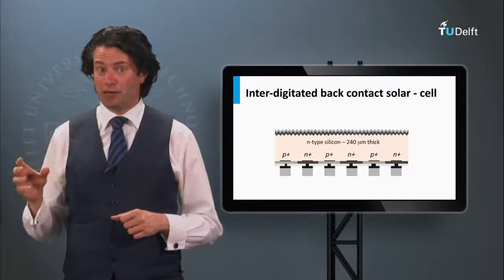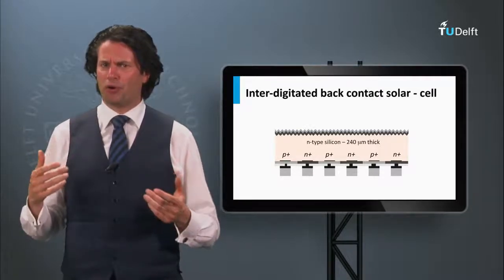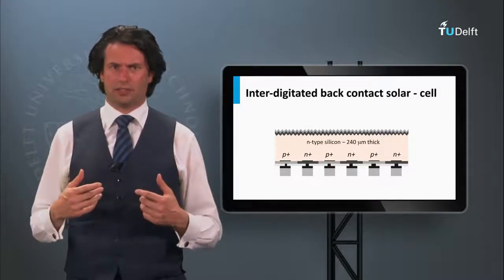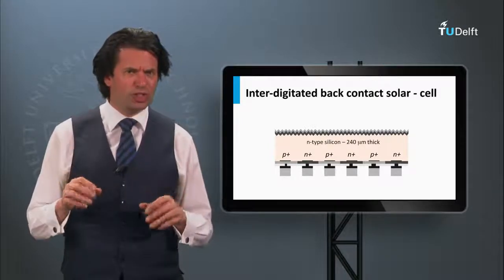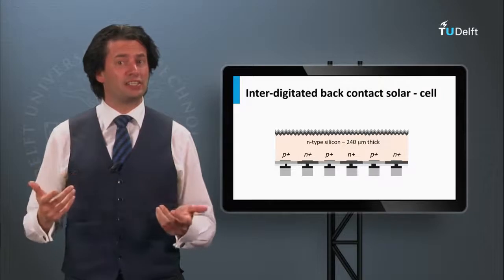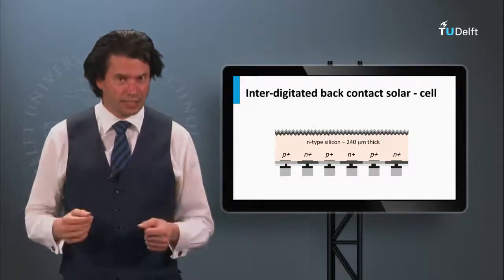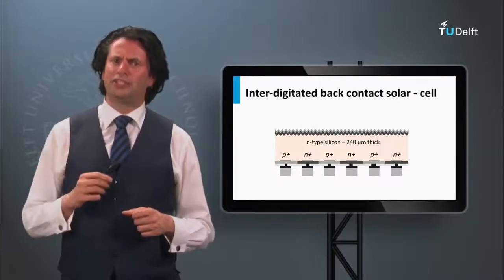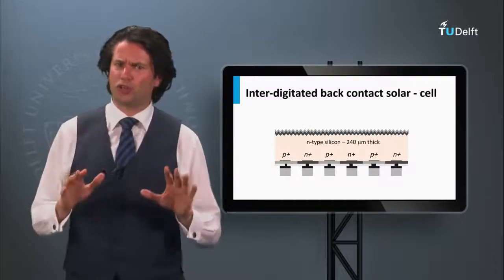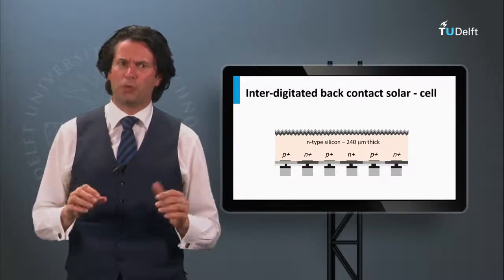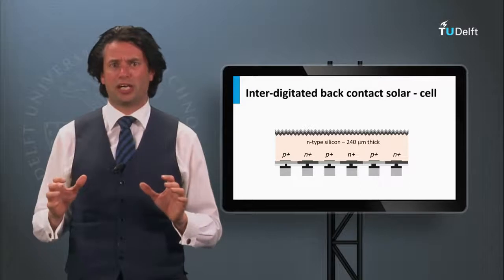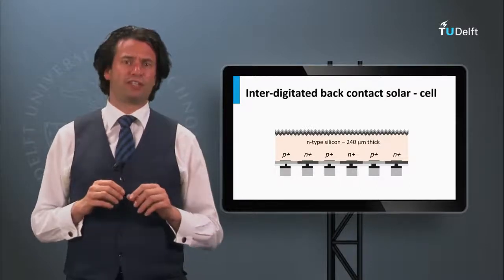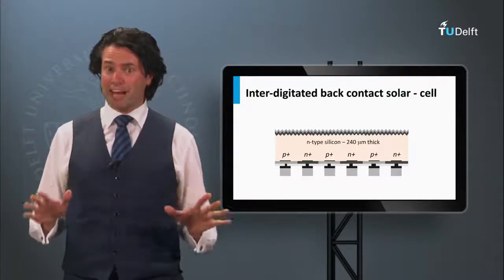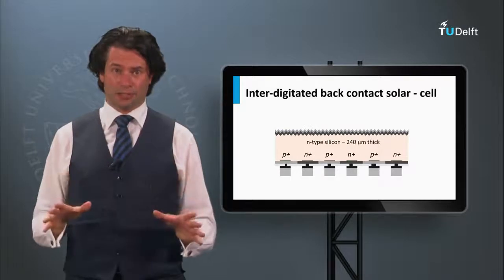In P-type wafers, simultaneously boron and oxygen are present, which under light exposure start to make complexes that act like defects. The light-induced degradation causes a reduction of the power output with 2 to 3% after the first week of installation. This effect is not present in N-type wafers.